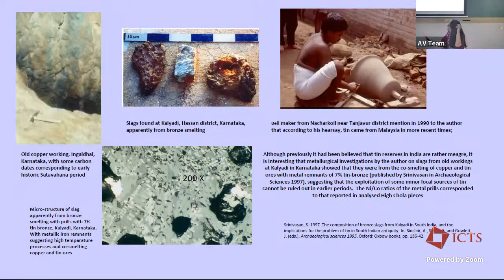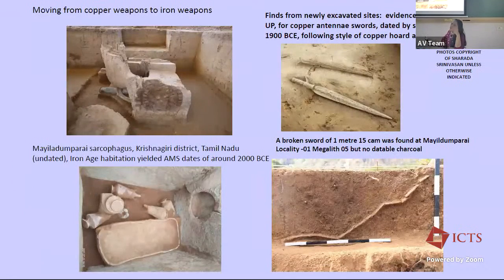For example, I found some really interesting evidence from the Kalyadi workings in Karnataka of bronze slags which had tin in them. These were actually bronze smelting slags because you had a lot of metallic iron, and so much metallic iron can only form when you've done smelting at very high temperatures. So these were some tin-containing ores which had been smelted at very high temperatures to get these kinds of bronze slags. So I think once we do more of the archaeology, we get more ideas. Oh, I don't have much time for iron, but anyway, I will try and do my best in the next 15 minutes or so.